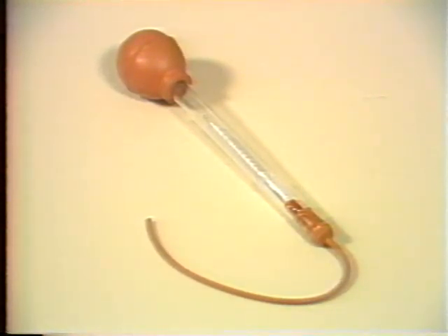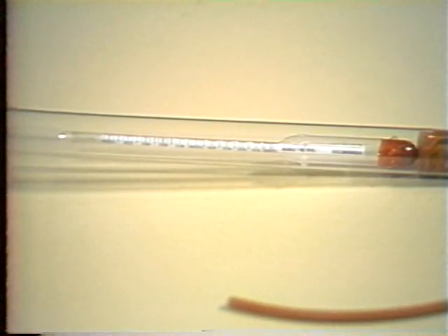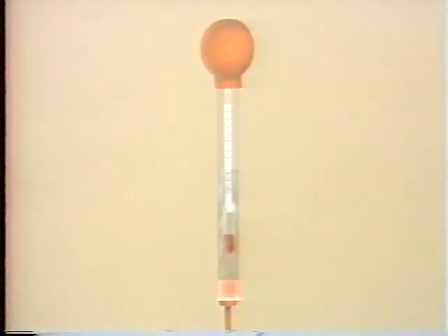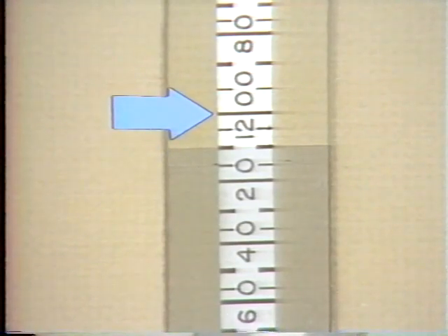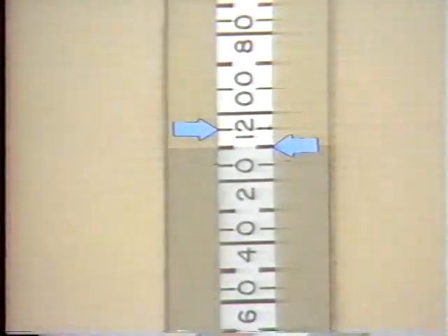On the job, we measure specific gravity with a hydrometer. It's basically a syringe, a glass barrel with a rubber bulb on one end. Inside the barrel, there's a weighted float that's marked off in units of specific gravity. If specific gravity is high, the float rises high in relation to the liquid. If specific gravity is low, the float sinks because the liquid supporting it is less dense. Here's what a normal specific gravity reading might look like. Read the scale right at the electrolyte level. This point represents 1.2. These scale divisions are each equal to 5/1000ths, so the reading is 1.210. You'll notice that the decimal point isn't used here.